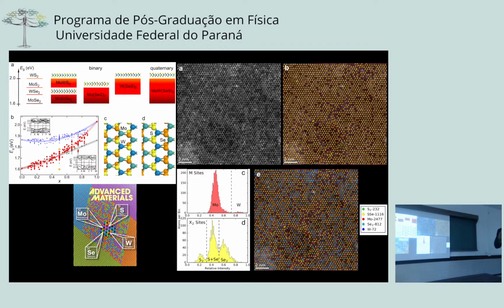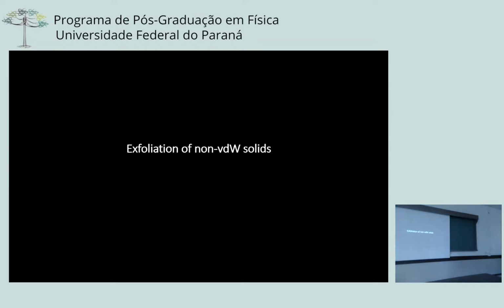Now the question is, is it possible? With the help of CVD, optimization of precursor, we can make this 2D material. With a high resolution image, we can probe these atoms and you can see all the different elements. We can nicely put them in two dimensions. Changing precursor concentration, you can tune the band gap of this material, right? So you can play around with a lot of mixing of different materials and make them at atomically thin scale.